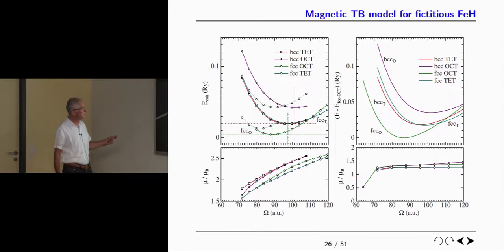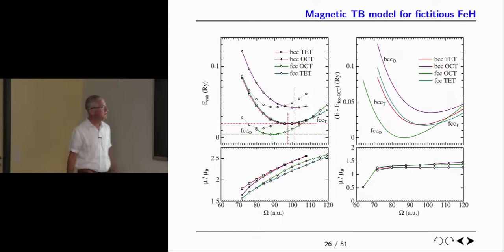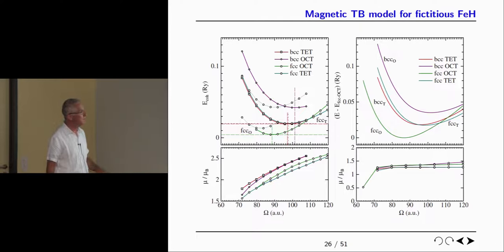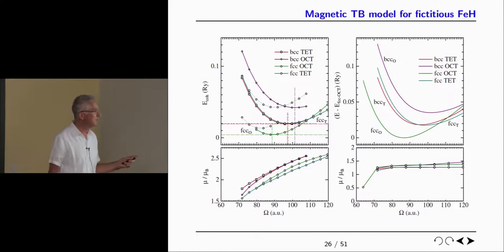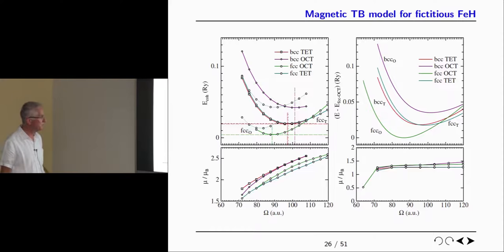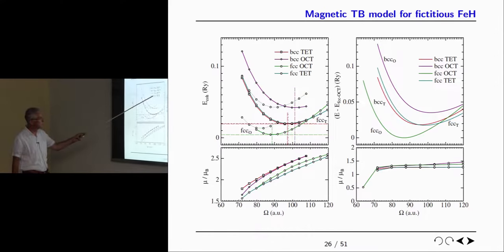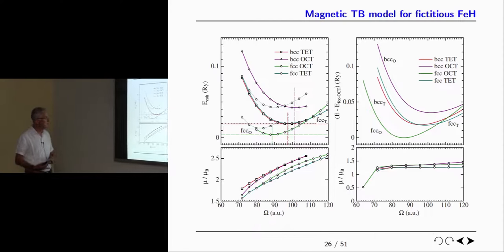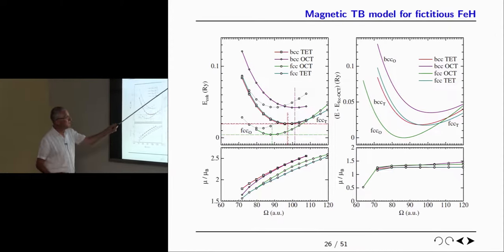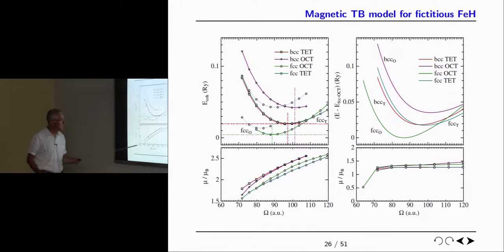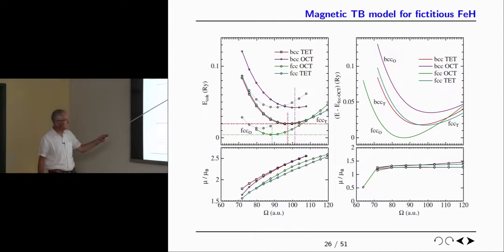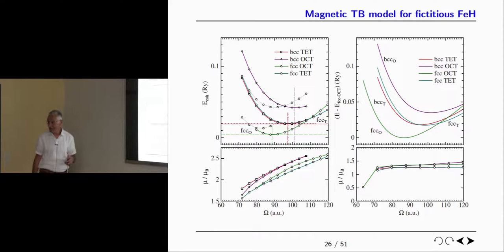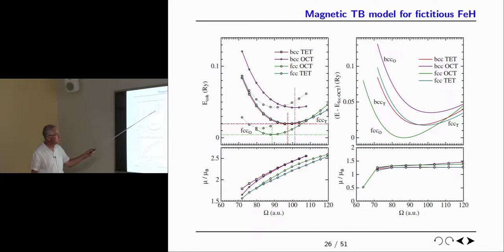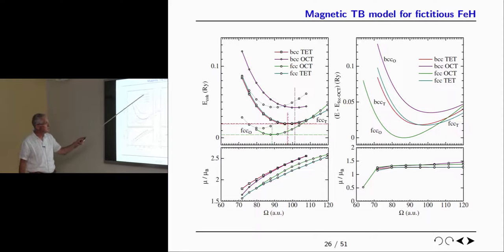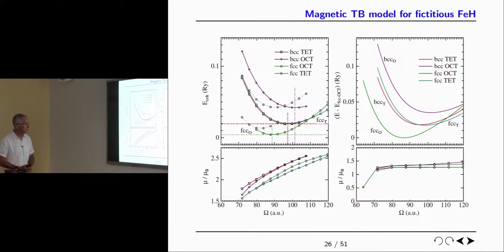So I considered these fictional, or fictitious, FeH crystals of hydrogen in iron, and using the density functional calculations, I calculated energy volume curves for these. And there are four possible, because you could use FCC iron or BCC iron, and you can put the hydrogen into either octahedral or tetrahedral sites. In the FCC case, if you put atoms into the tetrahedral sites, you create the zinc blende structure. And in the FCC case, if you put atoms into the octahedral sites at that stoichiometry, you create the rock salt structure. That's just an interesting point.